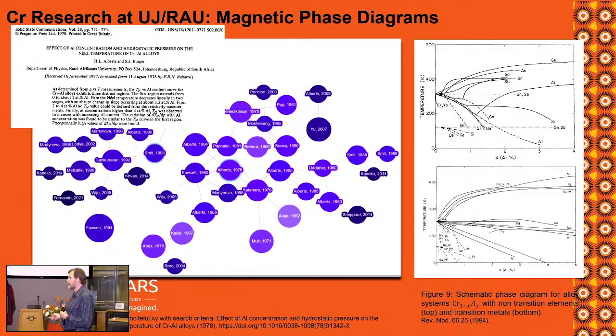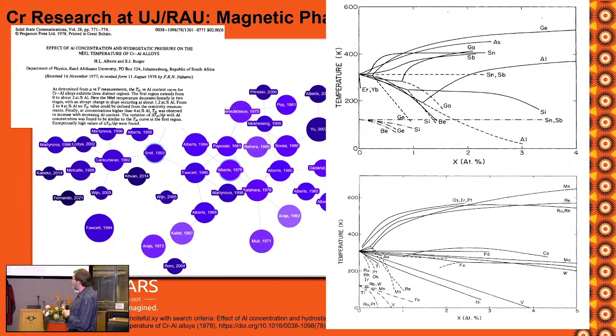There is a lot of other work, theoretical work on chromium. Chromium's antiferromagnetism was actually seen the first time in the 50s, using neutron diffraction. Now, most of the studies between 78 and about somewhere in the 2000s focused on this on the right. So this is a magnetic phase diagram. So remember TN, if you follow the curve, we actually track TN. This is as a function of different elements, the non-transition and the transition elements at the bottom. They have, because of the electron concentrations, different effects on chromium.